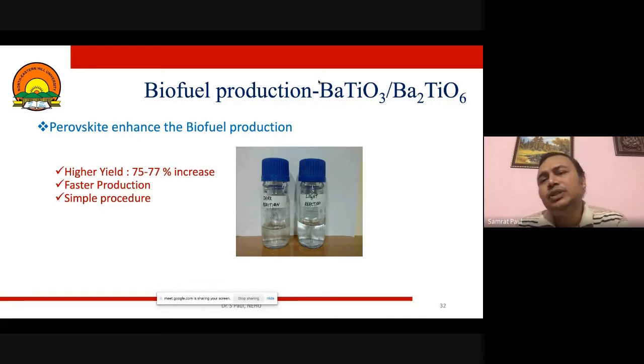We always use a homogeneous catalyst like KOH or something, and after synthesis, separation of KOH is a very tiresome task. It requires a high energy intensive process, and people leave it. So there is a wastage of catalyst, and we thought, why not use a heterogeneous catalyst which can be separated out very easily. So what we did is we used barium titanate mixed phase. So here we can see there are two phases. One is single perovskite combined with a double perovskite of barium titanate, and each nanoparticle has these two materials, thus again giving a mixed kind of advanced material that we have made.